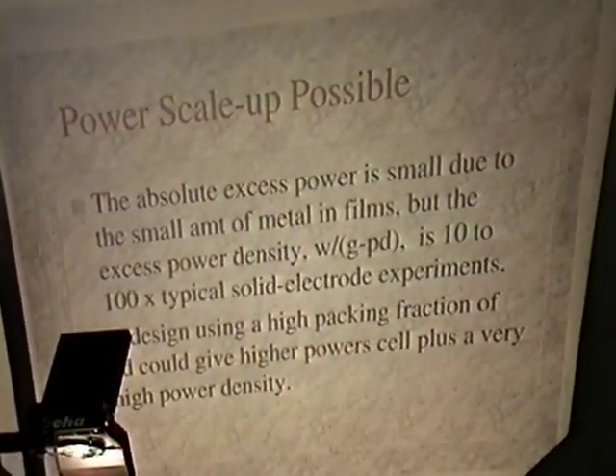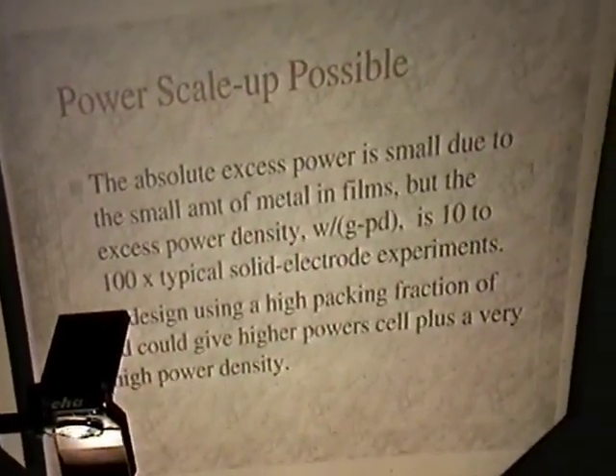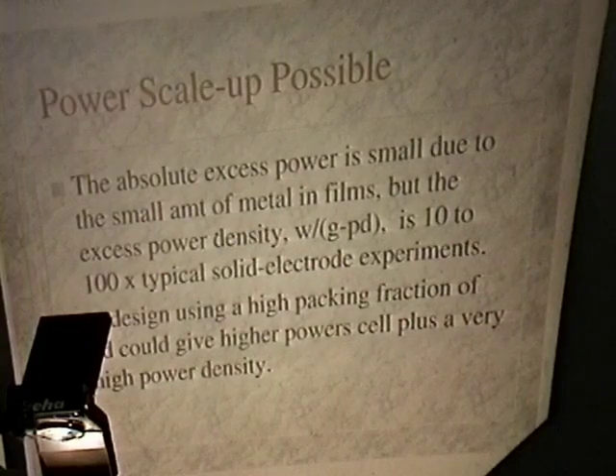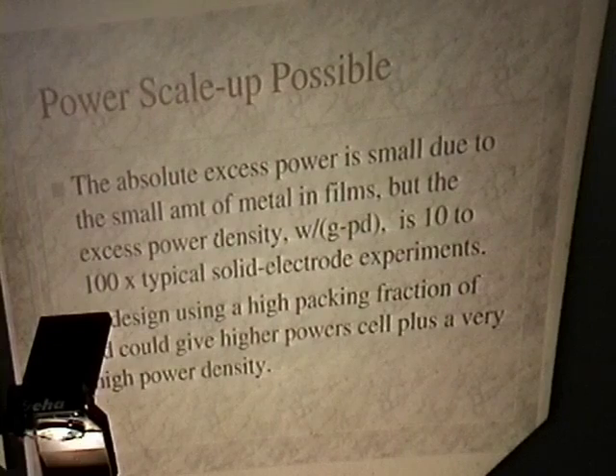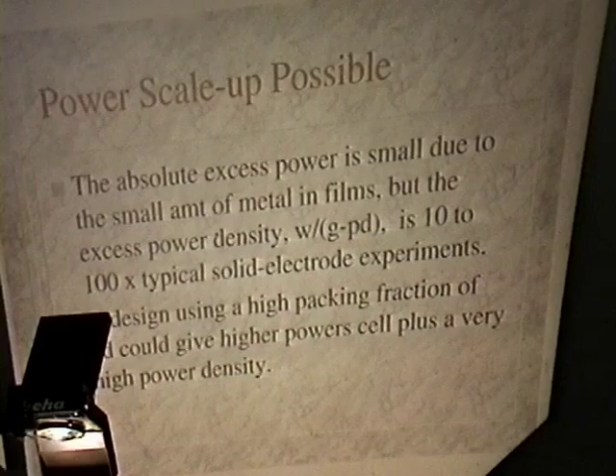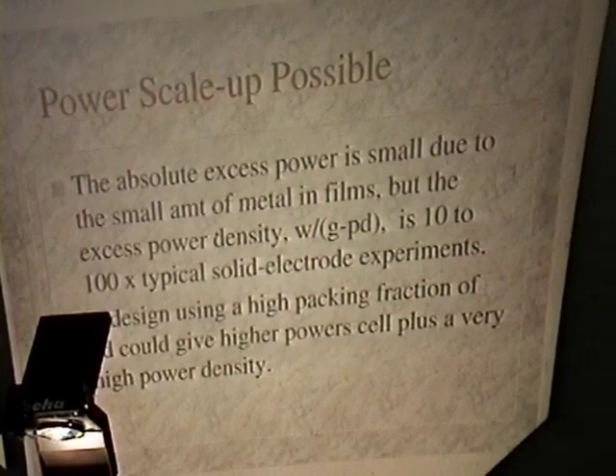So, in conclusion, I would point out, though, that the results I showed you seemed very modest when you consider that we only had micrograms of metal involved. This gives a very high power density. And the power density in these thin films, and I think in the wire experiments that were talked about, Frescotti and so on, always turn out to be exceedingly high in terms of watts per gram of palladium or watts per cubic centimeter of metal. And these numbers are something like 10 to 100 times the values for the solid electrode experiments or others that you see.